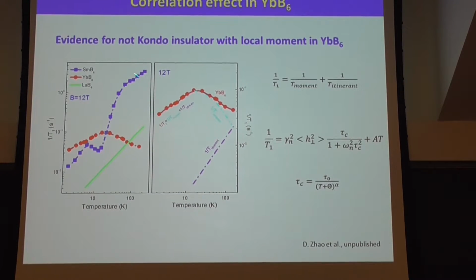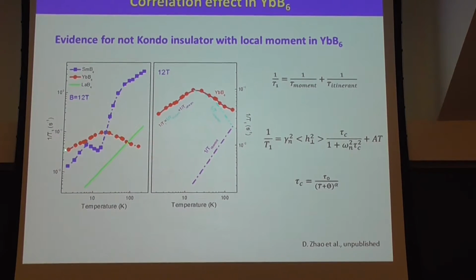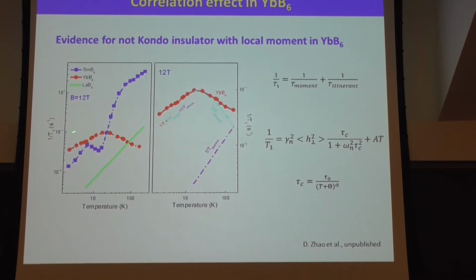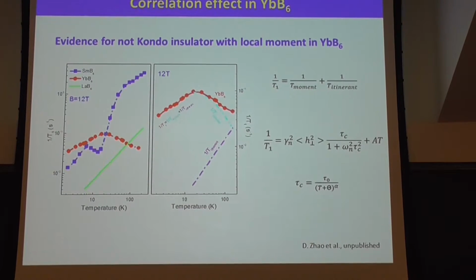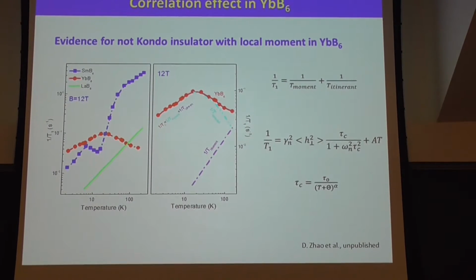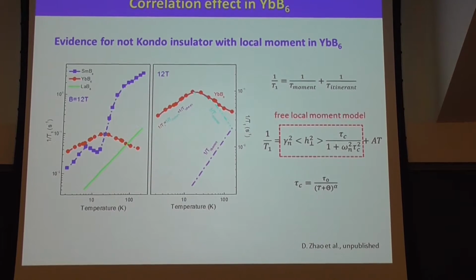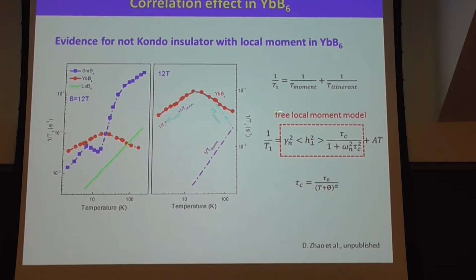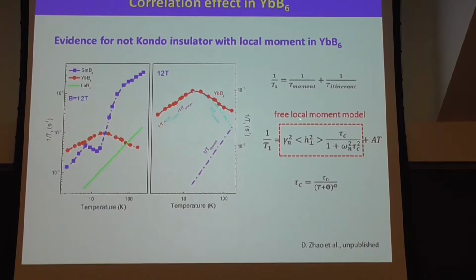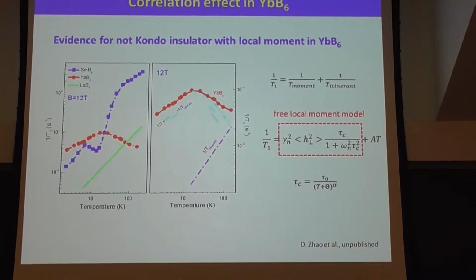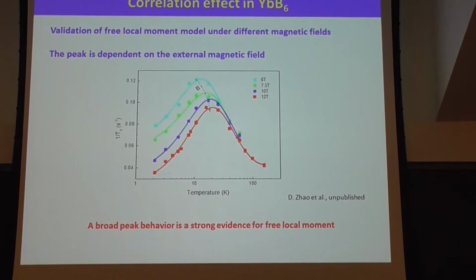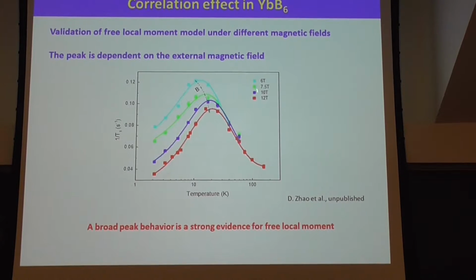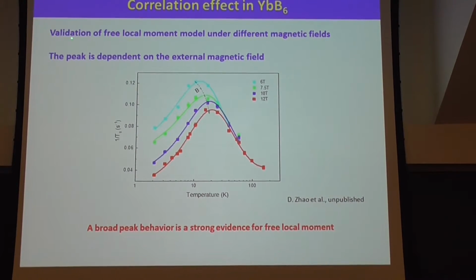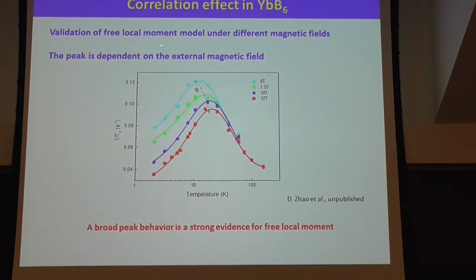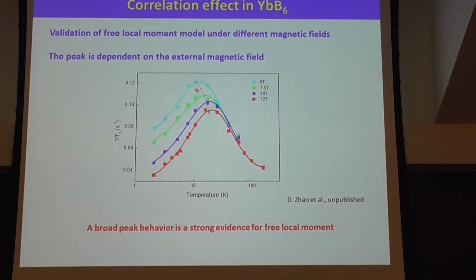This is not a Kondo insulator. Here you can see this shows some peak, which shows some free local moment. This material uses a fit with free local moment model, but it also depends on the field. We also use different fields, and you can see this peak is shifted. It definitely gives you the free local moment under different magnetic fields.